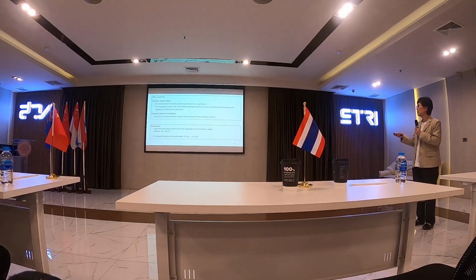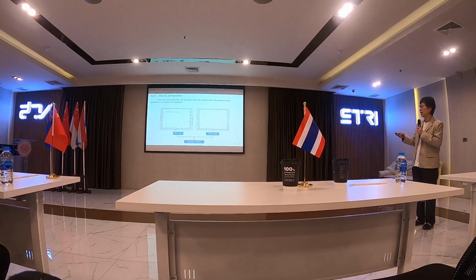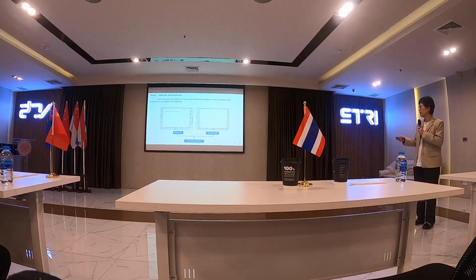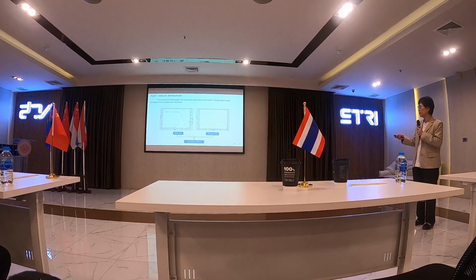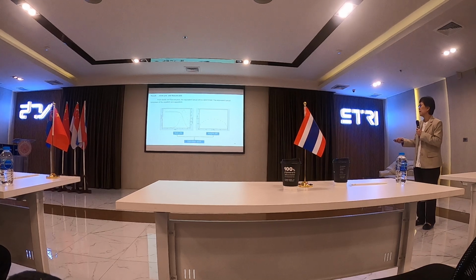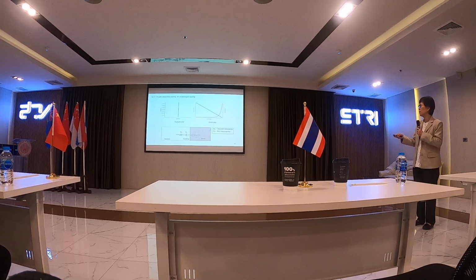Okay. Another technique is EIS. We apply a small potential with alternating current from high frequency to low frequency. We get the results as both the Bode and the Nyquist plots. From these we get the equivalent circuit.